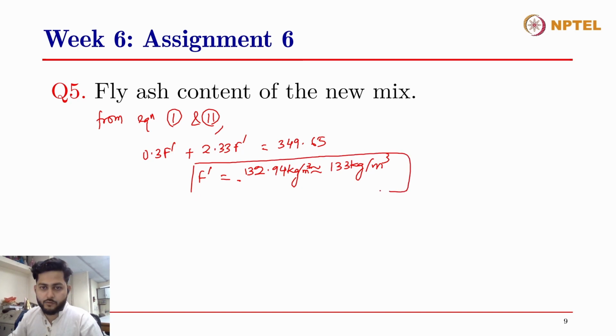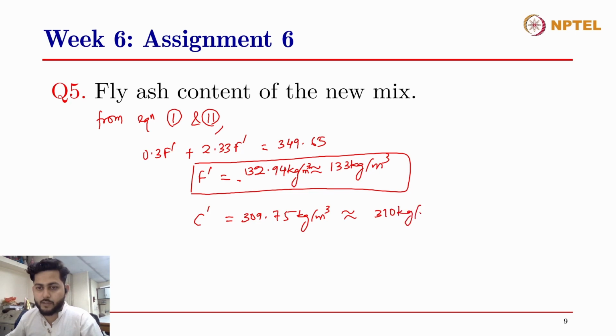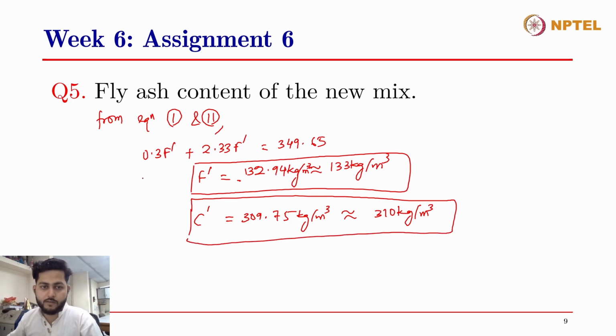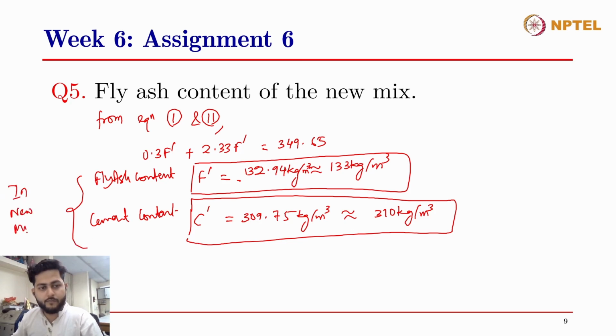Now F dash is equal to 133 kgs per meter cube of concrete, and from that we can calculate the C dash value as 309.75 kgs per meter cube of concrete. We can approximate this to 310 kgs per meter cube of concrete. So that is the value of cement content and the fly ash content in the total mix, in the new mix. So this is the fly ash content, and that is the cement content in new mix, right? 133 and 310.